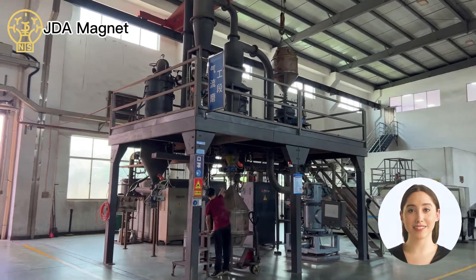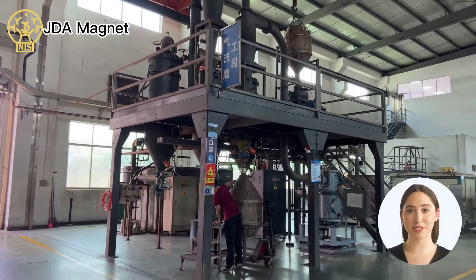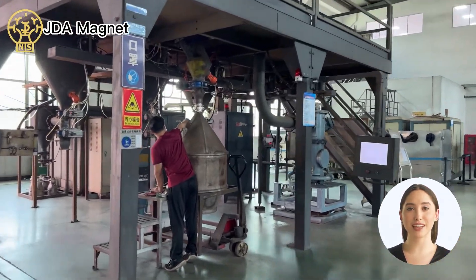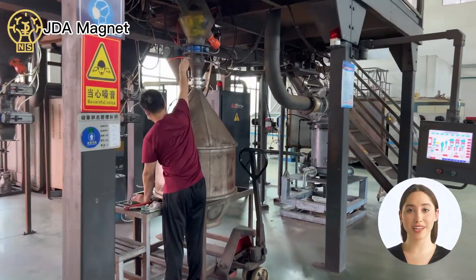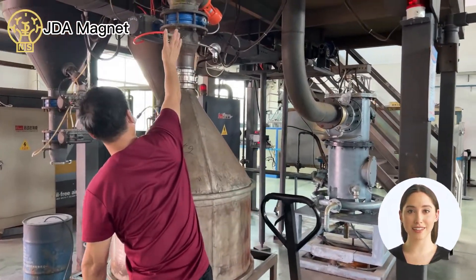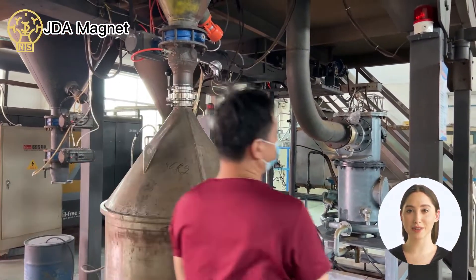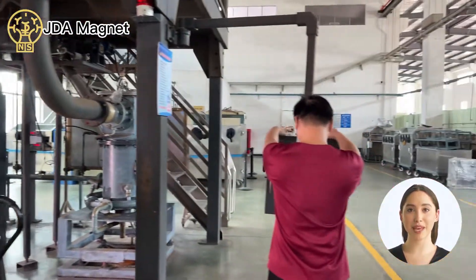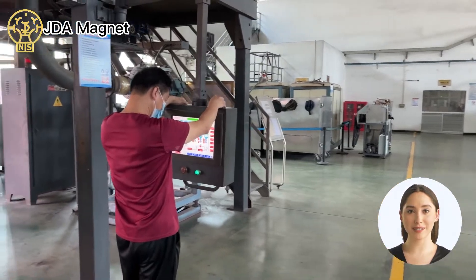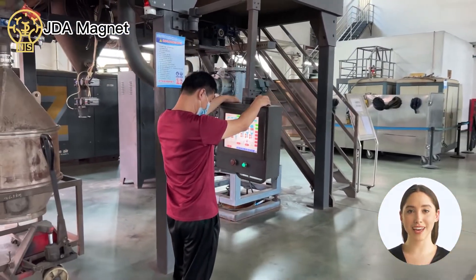After the HD process, the powder still needs to be further reduced in size through the jet milling procedure. The jet milling process consists of near-sonic confined jets of gas, usually nitrogen, creating a vortex into which the HD powder is introduced. The high-speed impact between the HD particles as they collide in the vortex causes a significant reduction in the average particle size.